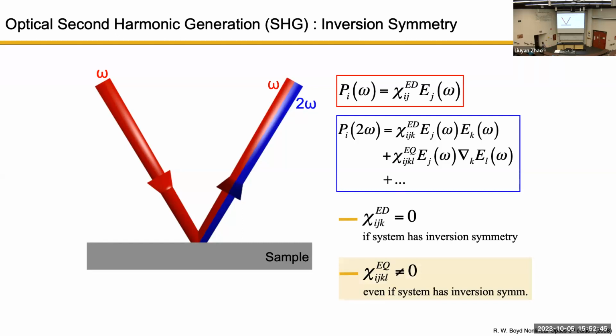So we can say, okay, when the leading order electric dipole is gone, what about the higher order processes? We don't have to consider higher order processes in linear optics because the leading order is always there. But in SHG, the leading order can be gone. So the higher order processes, for example, the so-called electric quadrupole process, are always going to be there, whether or not you have inversion symmetry. So with this knowledge, it's actually more correct to say SHG is there for any material you measure. It does not have to break inversion symmetry to have SHG.